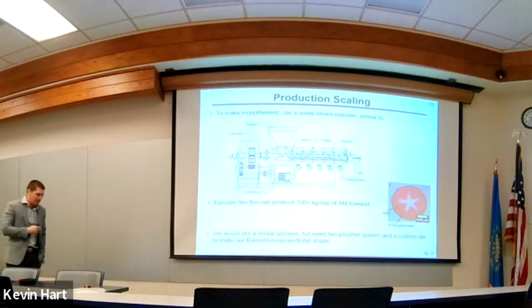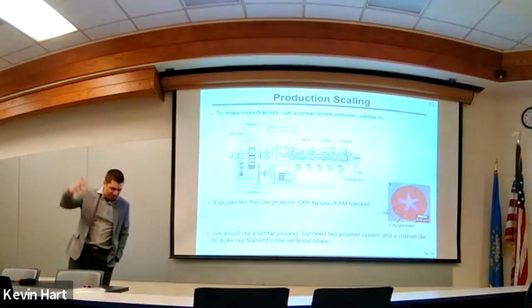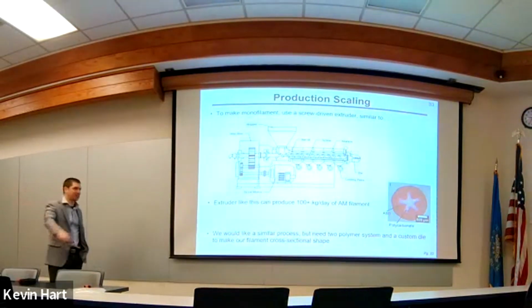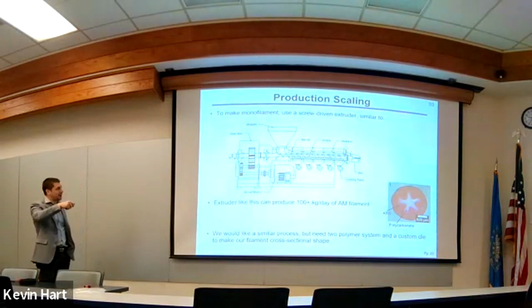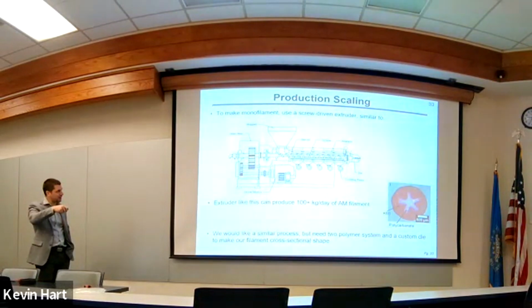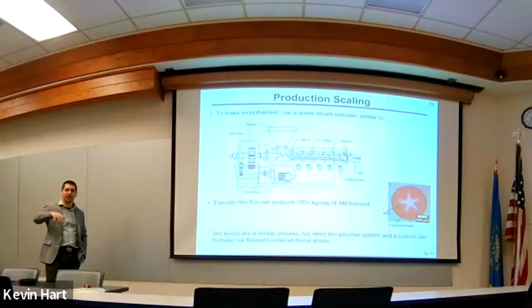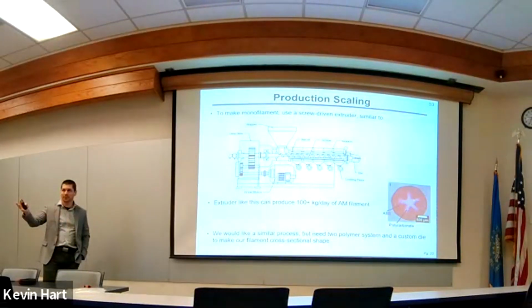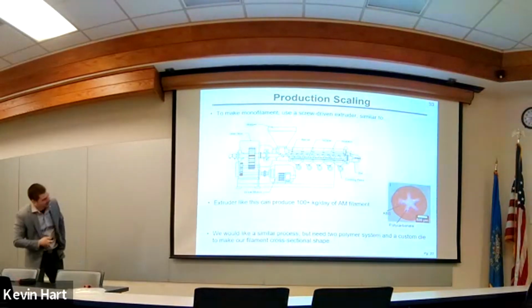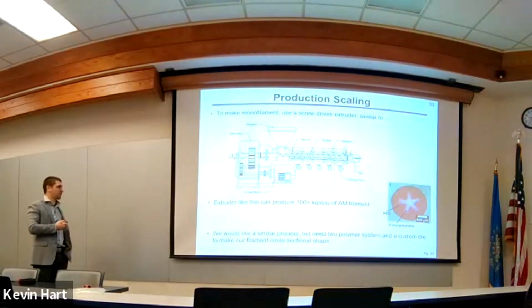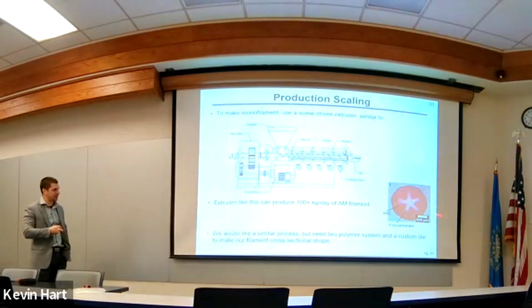All right. So how might we scale this up? Well, if you're going to make 3D printing filament normally, you would use a single screw extruder, something that looks like this. You've got a hopper where you put your pellets of ABS. You've got a screw being driven by a motor on the back end, pushing all of those polymer pellets forward, and then you have all these chambers that are heated to various temperatures. On the front end, you have a die. It's going to give you circular filament, and you can run this thing all day long, making tons and tons of filament. That's how most filament is made, at high rates of production. Then the question is, well, can we make something that looks like this to produce a filament that looks like this? All right?